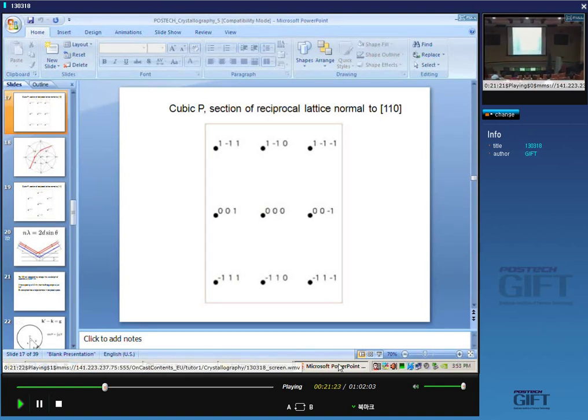And if you had a primitive cubic material, this is what an electron diffraction pattern with the electron beam coming along the 1 1 0 direction would look like. Of course, this is just a lattice. These are imaginary points. I haven't got any intensities on here as yet. We have to go on further to see what the intensities of these reflections would be. But this is the reciprocal lattice.